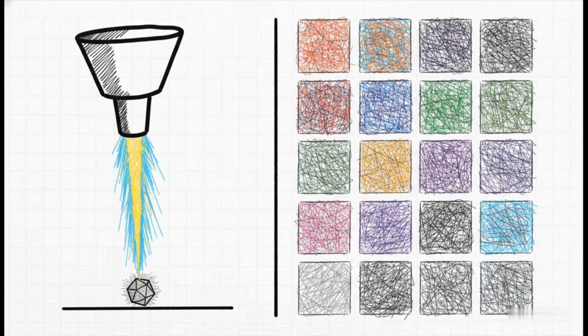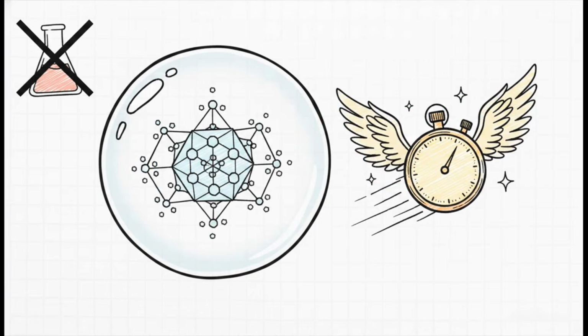You see the shape and you see the chemistry, all at exactly the same time. Superpowers 3 and 4 are really all about efficiency. The analysis is fast and it's non-destructive. You can get qualitative and quantitative elemental profiles incredibly quickly, completely without harming your super delicate nanosamples. Add to that the fact that there's little to no sample preparation needed.